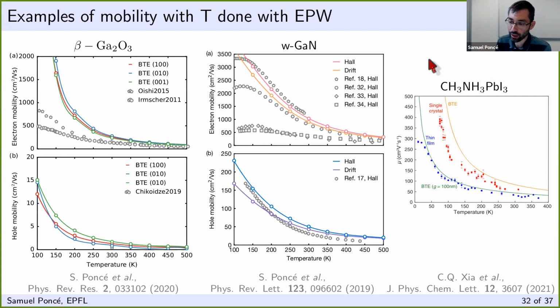However, you need to also consider the fact that the band gap has almost no effect on the mobility itself, right? The only thing that has an impact is the effective mass, so the change of band curvature. So if the band gap is very wrong, it doesn't matter at all. The only impact it will have on the mobility is if the band curvature, basically the electron velocity, changed, then it will have an impact. So it's not very crucial, I think, to describe the change, except if the band curvature changed a lot due to those renormalization effects, but I don't think it's the case. For silicon, for example, it's maybe 1, 2 percent, very small. Yeah. Thank you.